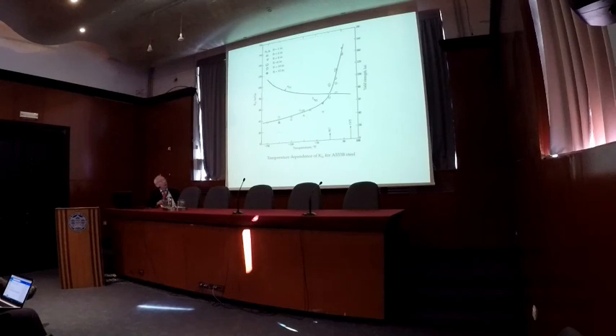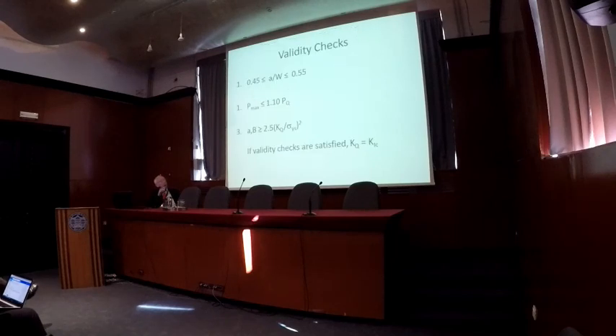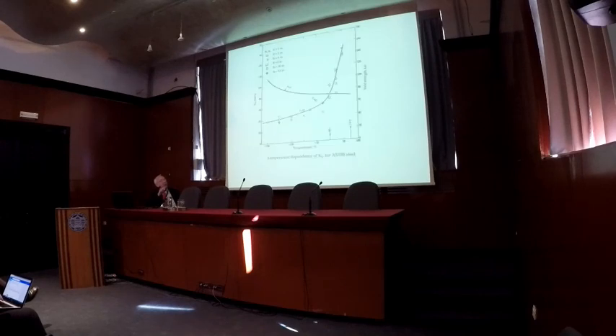One of the things that is a problem is the size by this criterion. And here was a nuclear pressure vessel steel that was tested, and steels have brittle fracture and low toughness at low temperatures. And as you go higher in temperature, you get into a transition stage where the toughness goes up rapidly. Now, this is done, unfortunately, in degrees Fahrenheit, but here would be about minus 50 Celsius, minus 100 Celsius, minus 150 Celsius. And K1C is in ksi root inch, but the difference between this and MPa root meter is only about 10%, so it's very similar.